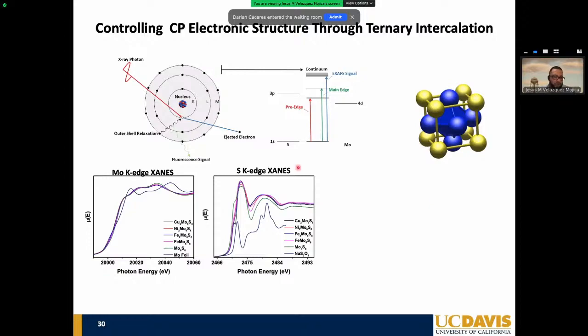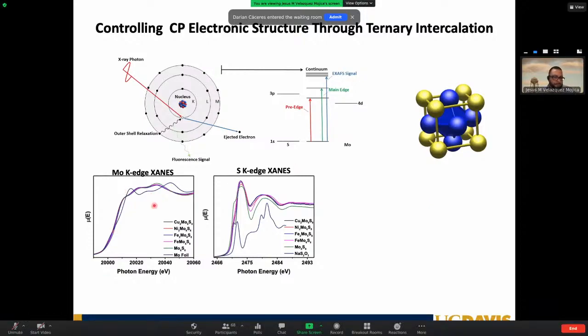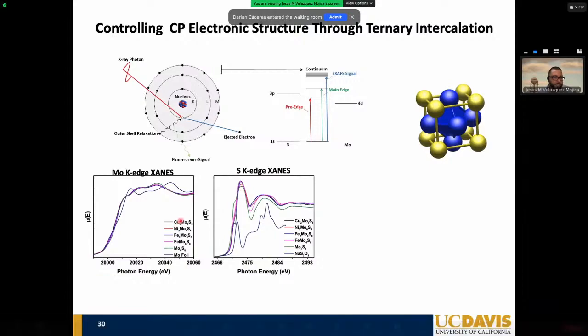What you're seeing here is the molybdenum K-edge data from all these different Chevrel phases that have been intercalated with copper, nickel, iron, and we obviously compare with molybdenum foil and with just the binary molybdenum sulfide. If you look at the pre-edge region, which is the region I'm highlighting here, there is little to no action. There are no features there. And it's actually not that surprising. This is just a metallic core, and it's really just letting you know that indeed we have what we think we have.